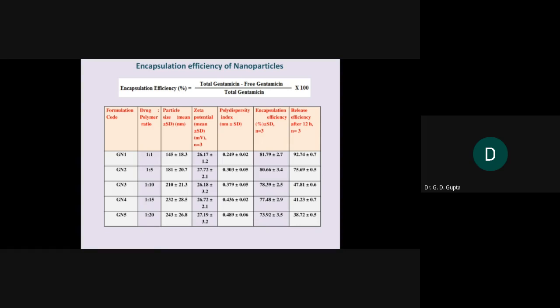Okay. Now second, again we can see the encapsulation efficiency. You can see for formulation number GN1, the encapsulation efficiency is comparatively good, that is 81.79, and in the release study for 12 hours, about 92% of the drug gets released from the encapsulated system.